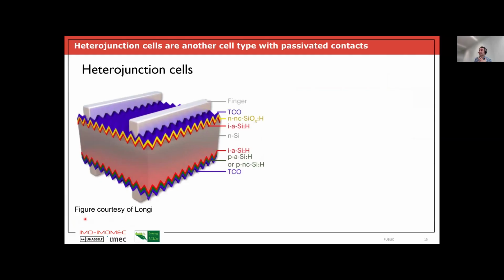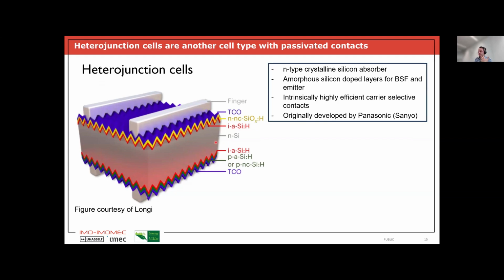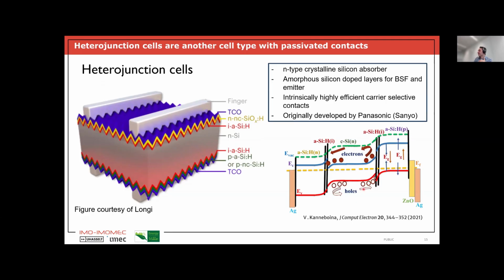A second type of passivated carrier selective solar cell that is being mass produced more and more is a so-called heterojunction cell. So this is a quite different way of making the silicon solar cell. It's called heterojunction because now we use the crystalline silicon wafer, but we put amorphous silicon layers on top of the surfaces to passivate. So again, this leads to very good surface passivation at both rear and front. You get carrier selective contact. So on both sides now, you are only attracting one type of charge carrier, and you are pushing away the other one for extra surface passivation.